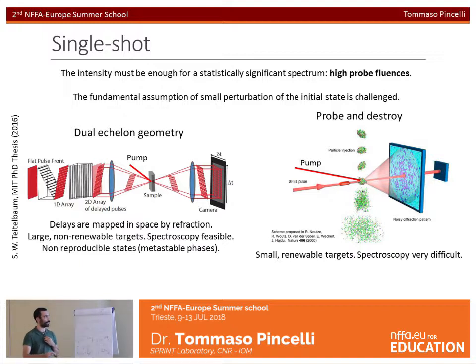On the other hand, for the single shot, we have the probe-and-destroy approach, in which we excite the system and then at a controlled delay we send a pulse that is intense enough to look at the system, but also intense enough to destroy the system and short enough to see the system before it's destroyed. So this requires small and renewable targets and makes spectroscopy very difficult because, once again, the probe pulse perturbs significantly the state of the system. It's mostly used for diffraction and imaging of small objects.